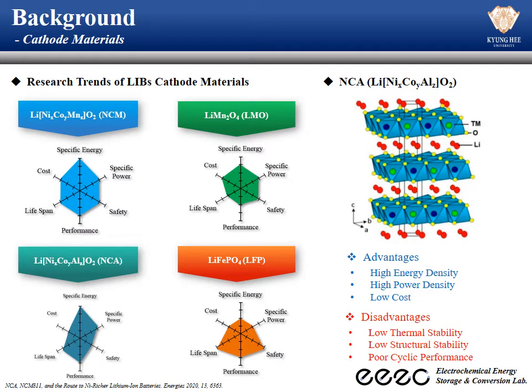Materials used as cathode materials for lithium-ion batteries include NCM and NCA as a layered structure, LMO as a spinel structure, and LFP as an olivine structure. Among them, NCA can have high energy density and power density while being inexpensive. Because of this reason, it is in the spotlight. However, the low structure stability and thermal stability of NCA is a major disadvantage, and due to this, the cyclic performance is also low, making it unsuitable for use for a long time.